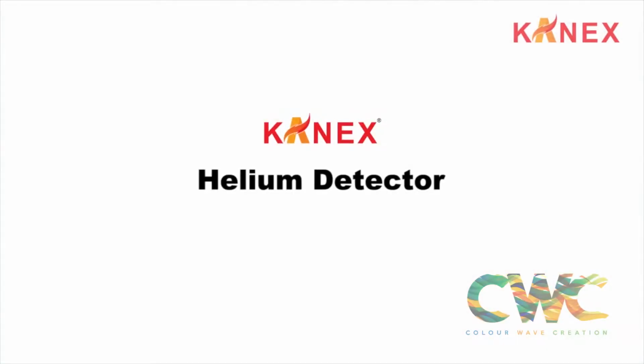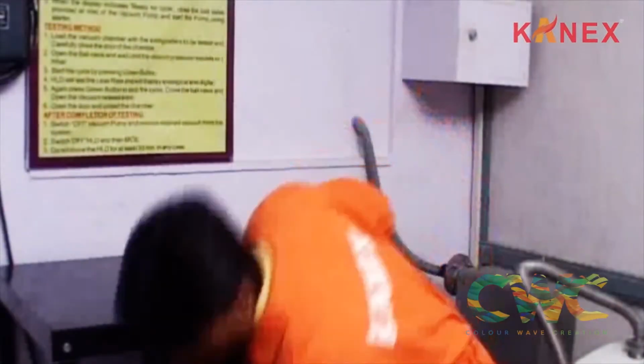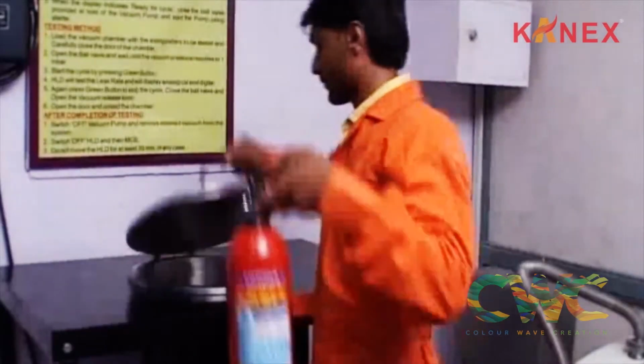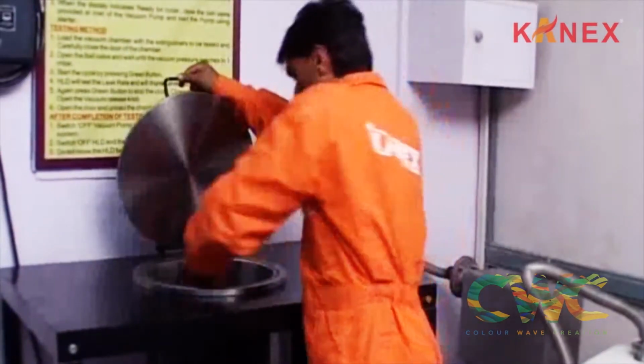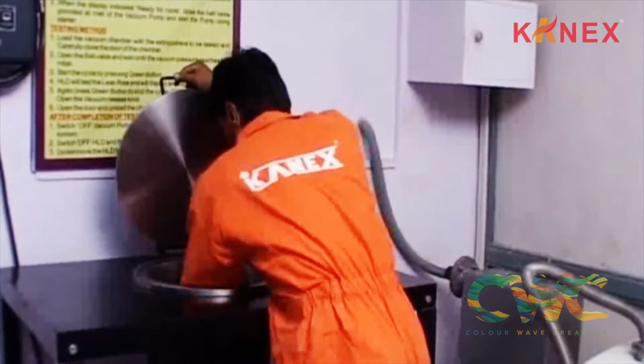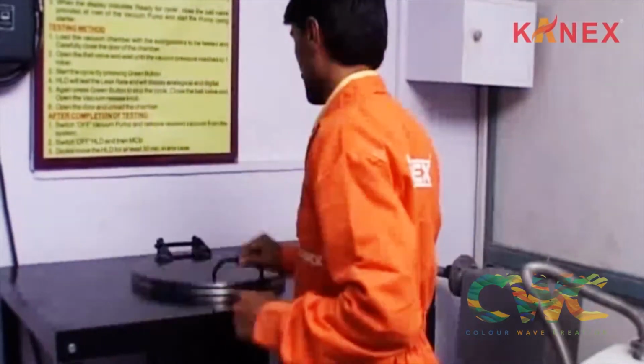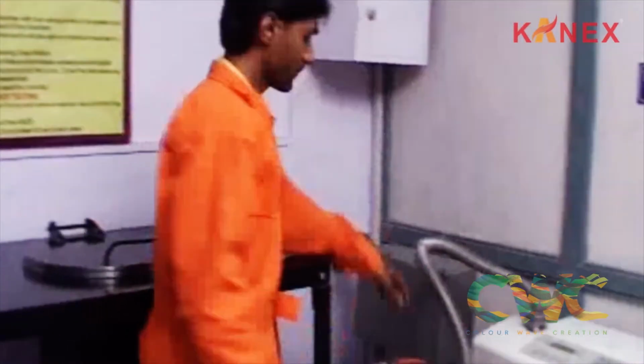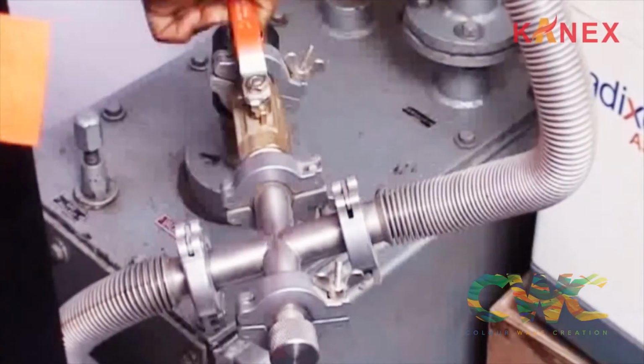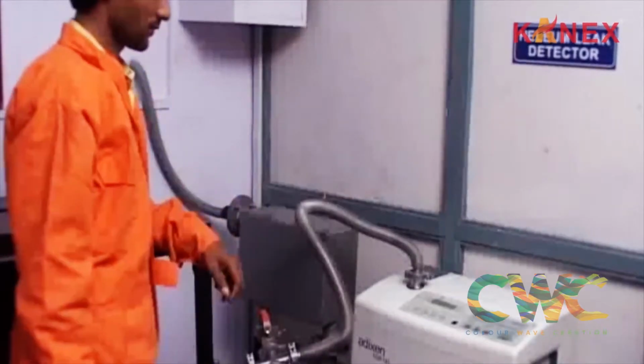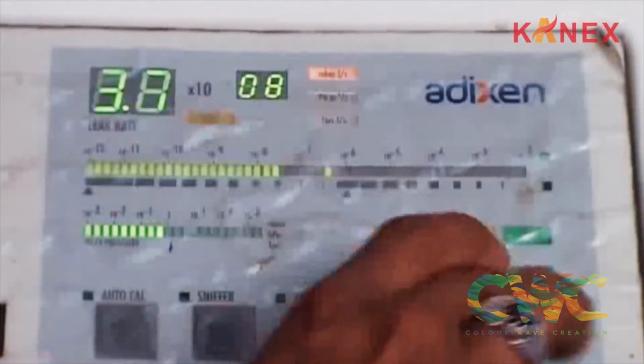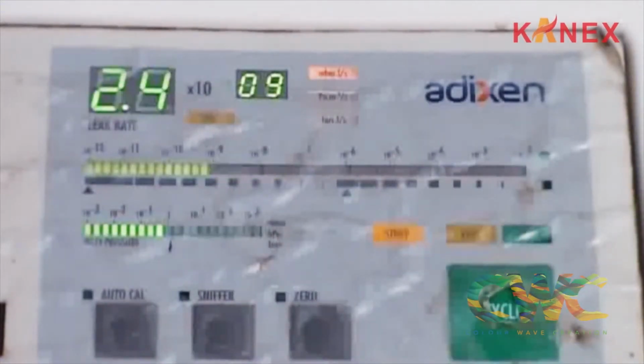Kanex tests each extinguisher in a helium leak detector, and each extinguisher passes through a vacuum chamber in case of having a high leak rate that is greater than 10E minus 6 millibar liter per second. Only when the authenticity of the extinguisher is confirmed does it proceed for final packing and dispatch. Very few Indian companies are equipped with this facility to avoid complaint of pressure drop.